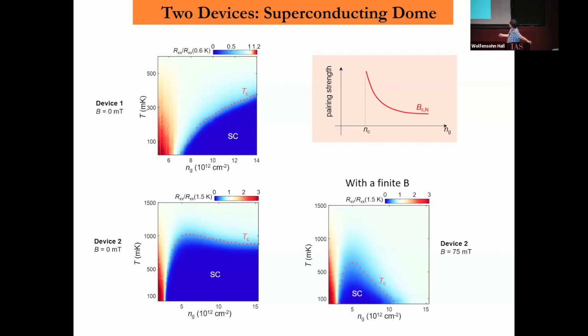What's even more interesting in this device is that now you apply some magnetic field. Because the pairing strength here is weaker, you can expect that we actually kill the superconductor here first. So then you're going to have a dome, which is exactly what we see. You apply some magnetic field, 75 millitesla, then we see a dome where the superconducting state is now in the middle, and at high density you don't have superconductor.